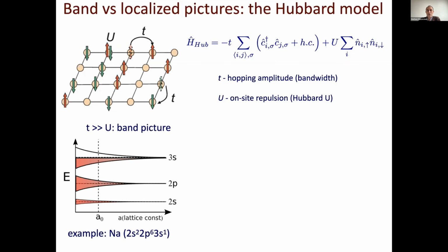In a band structure language, which is the one that we naturally use in approximate DFT, that would imply a metallic ground state, okay? Because we half fill a band, and there's no way to escape having the half filled band of the, in this case, 3s states.